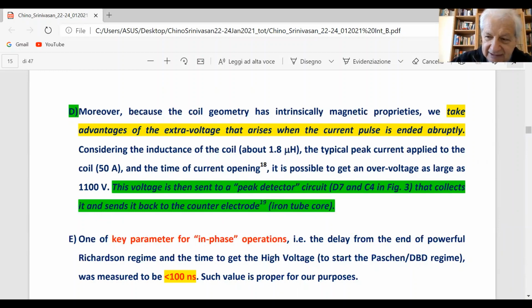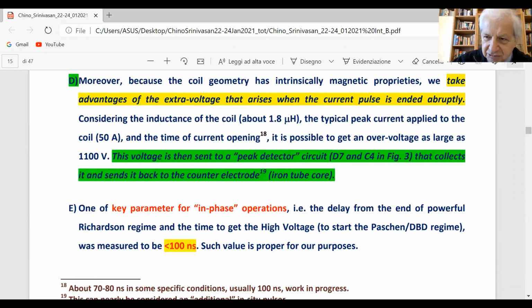The procedure to have the extra pulse for the Paschen regime is a little bit original. Usually when the coil stops the current, there is an extra voltage that is considered deleterious because it can damage the wire itself or the pulsar. But we use the extra voltage: we collect it and send it back to the wire to have high voltage to produce the Paschen regime, so the discharge. All this procedure is made in situ with a delay time of only 100 nanoseconds.